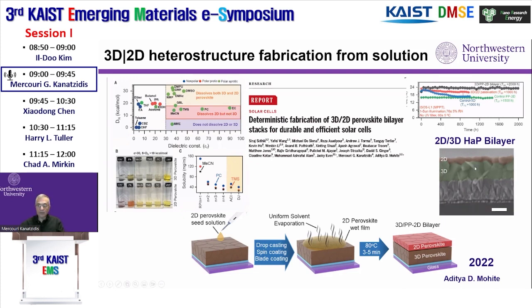And it wasn't possible because the solvents people were using for the 2D casting over 3D were destroying the 3D layer underneath. So we did a systematic investigation of solvents and found that, as you see here in the upper left, there are two properties that determine the solubility of 2D perovskites in these solvents. One is the donor number. This is basically a coordination number, ability to coordinate as a Lewis base, shown here, and then the dielectric constant of the solvent.